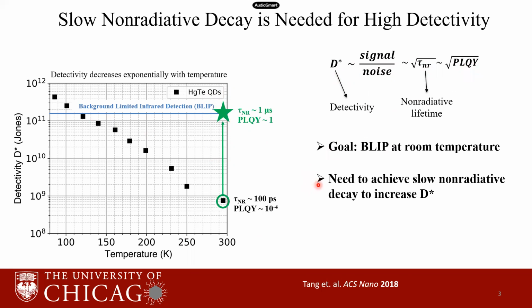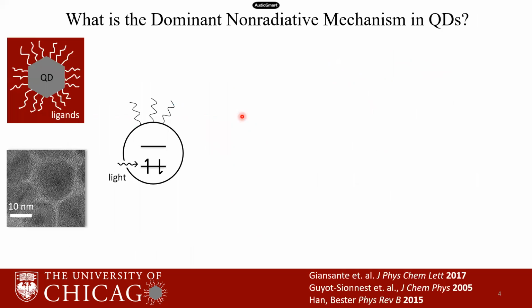Right now, the quantum dots suffer from a fast non-radiative process, which is of the order of a few hundred picoseconds, and the quantum yield around 10 to the minus 4. So in order to make efficient mid-infrared detectors having background limited performance near room temperature, it is necessary to design quantum dots which are bright and have a slow non-radiative decay. Before we can slow the non-radiative relaxation, it is necessary to first find the mechanism of relaxation.